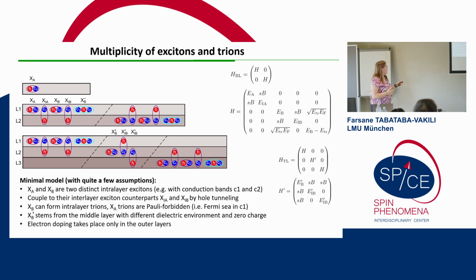And then, as we dope, XB can form a trion by binding to a second electron in the lower energy conduction band. So we believe that the Fermi level, in our case, lies in C1 with no additional charge in C2. And this is also why we do not observe any trions of XA, because these would be Pauli forbidden, because we cannot have two bound electrons in the same conduction band due to the spin polarization.